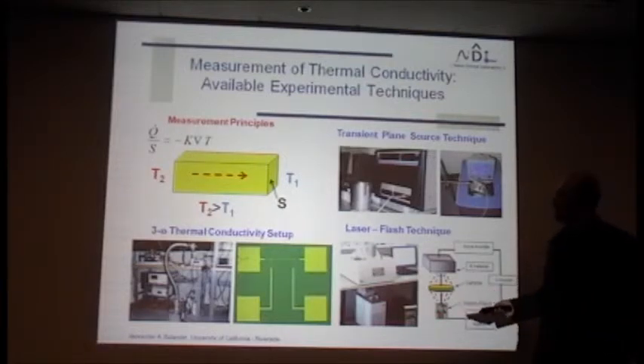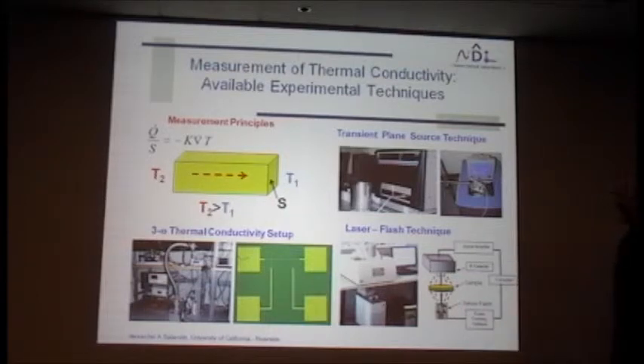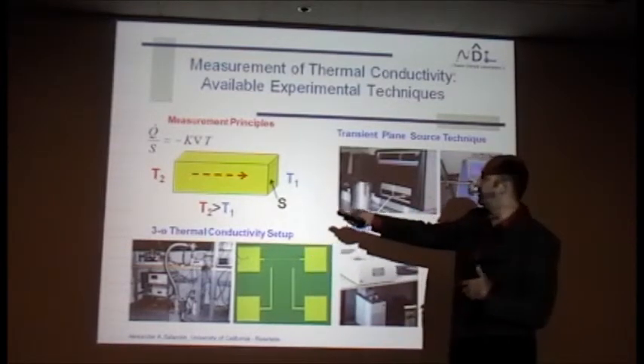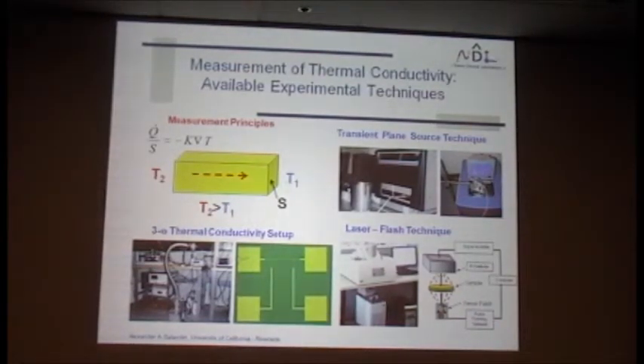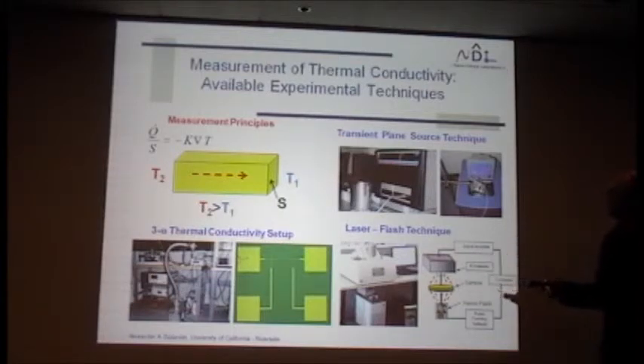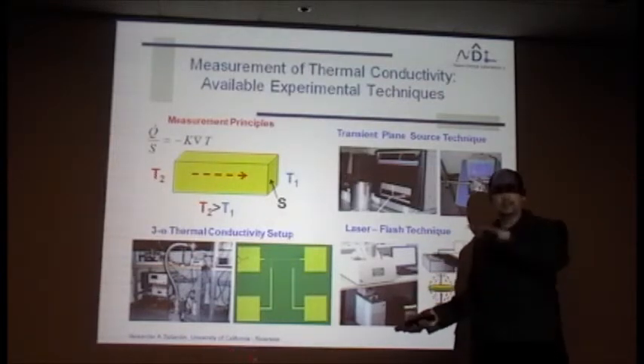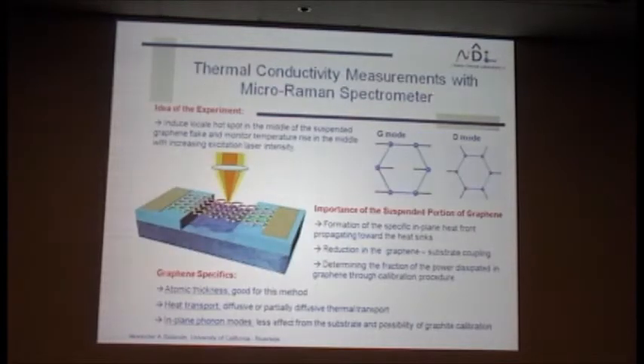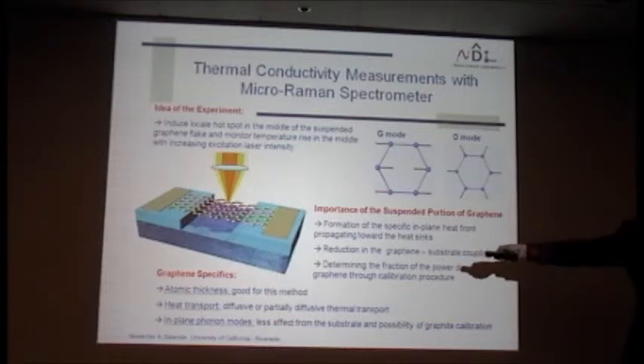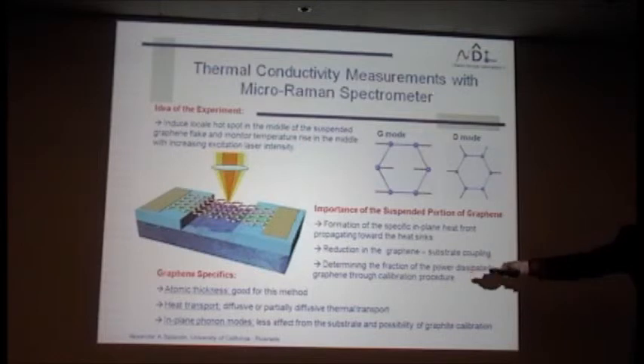So you have to look at what other materials can have pretty high thermal conductivity and try to incorporate them into the chip design. In this sense, graphene was of interest. I first discussed measurement with Andre Ferrari around 2007, but then figured it was probably useless — you cannot measure the thermal conductivity of something with atomic thickness. The measurement principle requires applying a temperature gradient and knowing the geometry. The instruments I have in my lab — hot disk, laser flash, 3-omega — do not work for graphene. But after we had the temperature-dependent Raman studies, we thought we could use this geometry: even if thermal conductivity is very high, because the cross-section is small and heat has no way to escape, we can measure thermal conductivity.